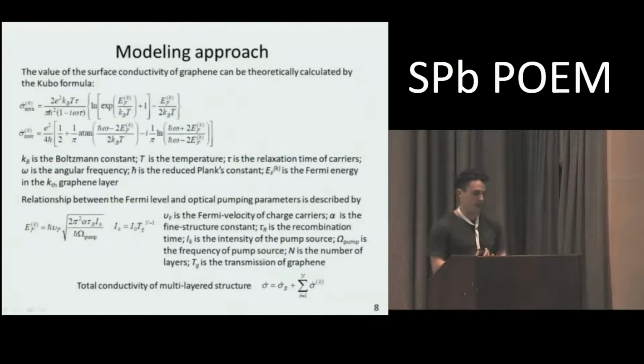The correct way to describe graphene is to use the surface conductivity, which can be calculated by using the Kubo formula. It takes into account both contributions from the intraband and interband transitions of carriers. The tunability is achieved by adjusting the Fermi level of graphene. In our case, we use the optical pumping, and the relation between the Fermi energy and the parameters of the optical pumping source was described by that expression.